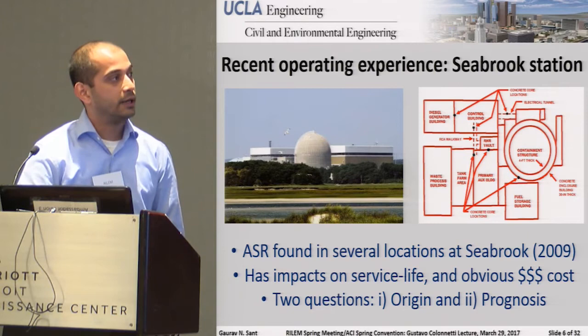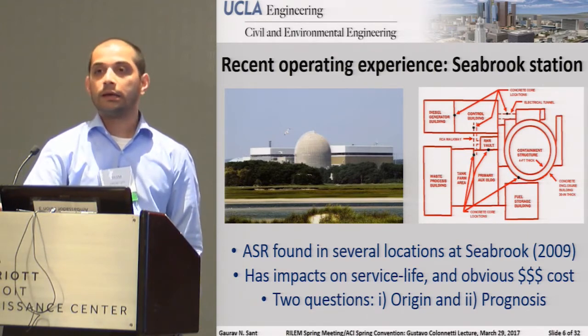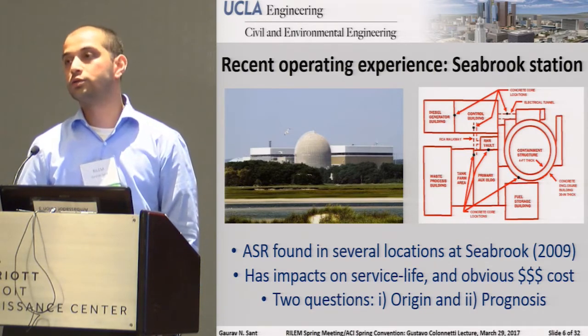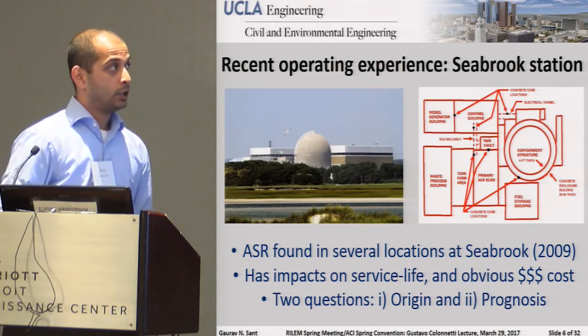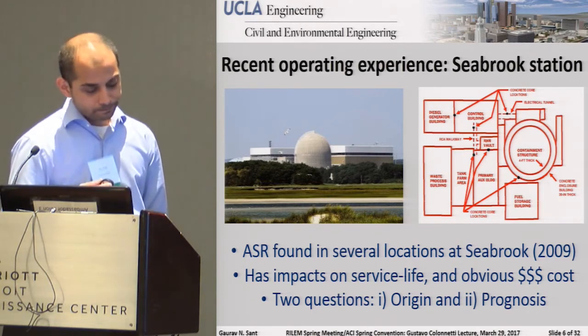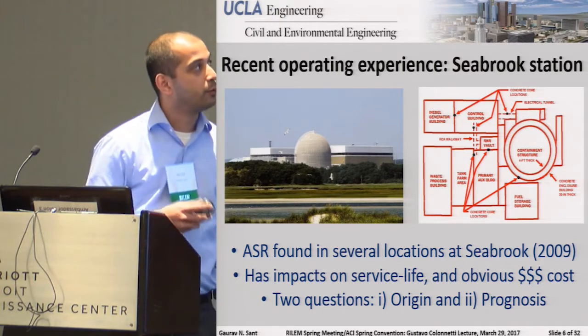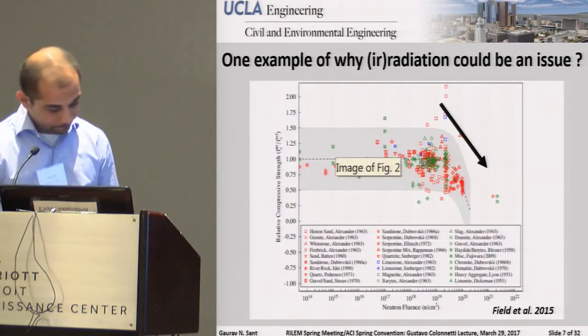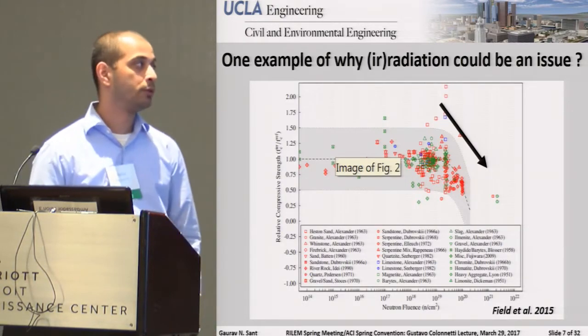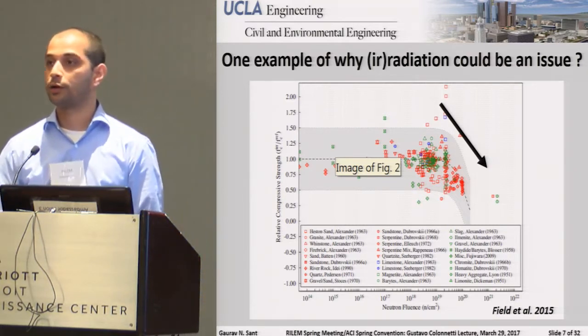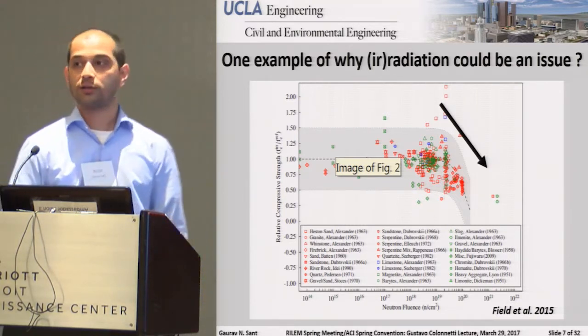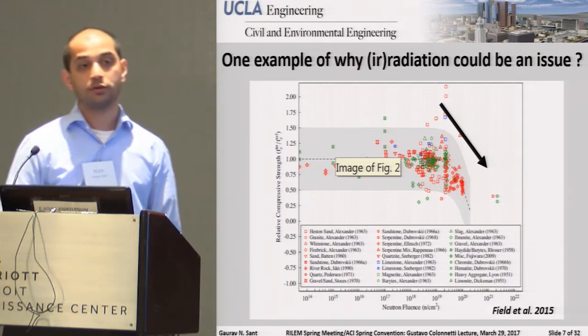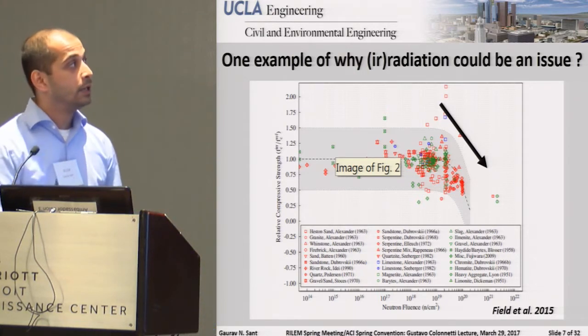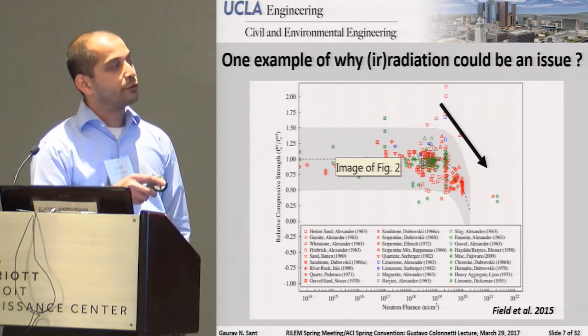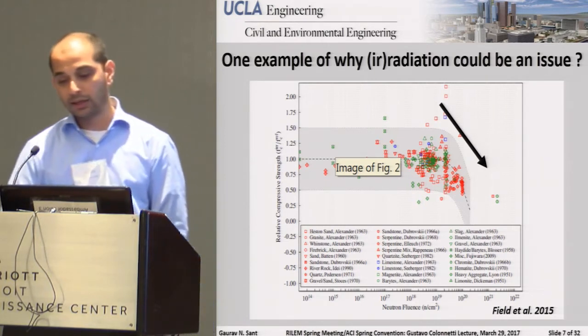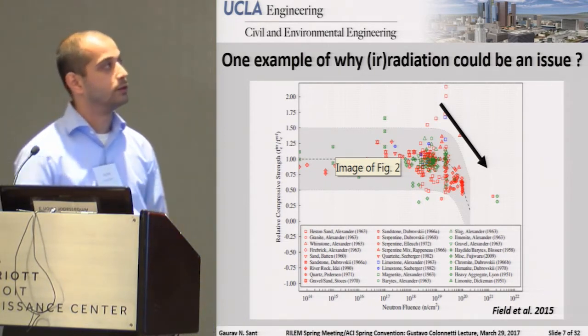The question that was specifically important to address in this case is, can ASR be induced because of radiation exposure? So why is this really important? There's quite a bit of work which has been done over maybe the last 50 years or so, where people have taken concrete containing different aggregates and exposed it to neutrons. This might be either simulated neutrons or real neutrons in test reactors. And you see interesting trends, and this is data that was compiled by Kevin Field at Oak Ridge maybe about 2 or 3 years ago now.